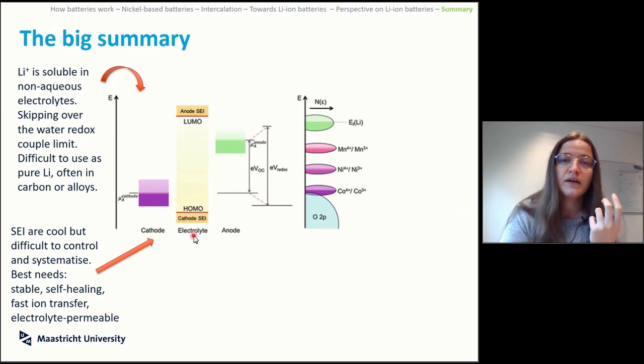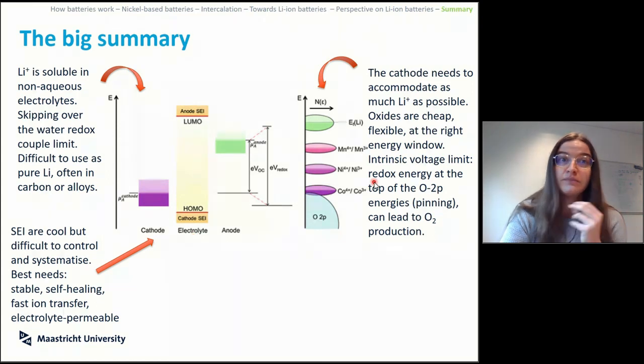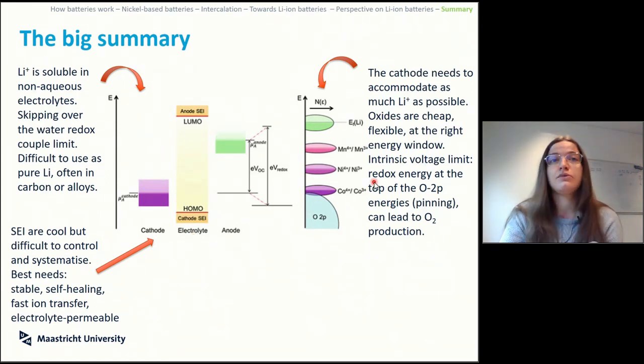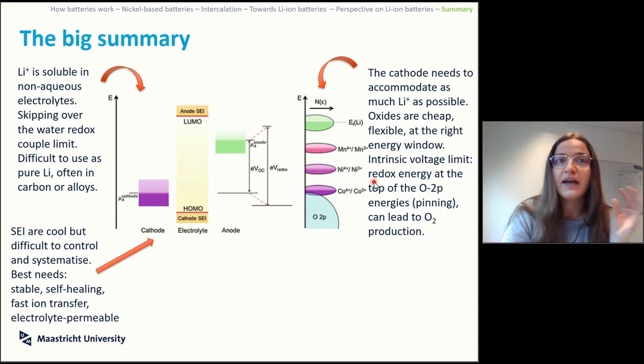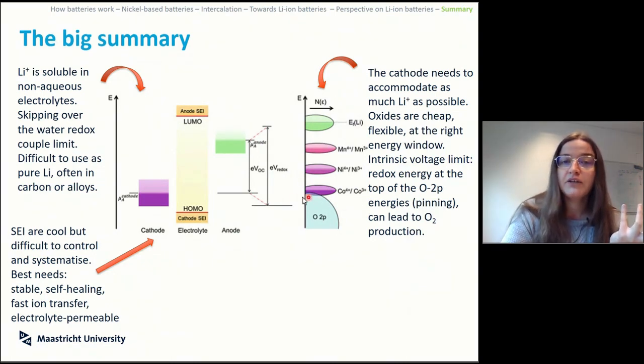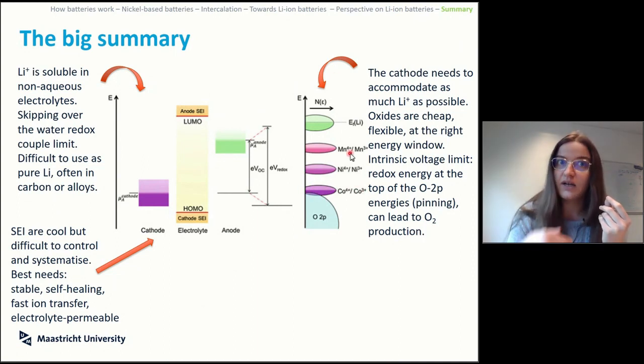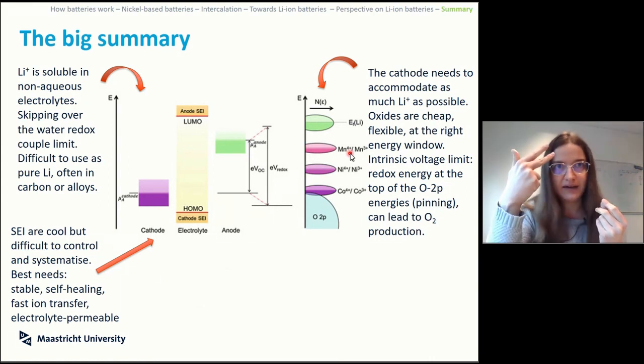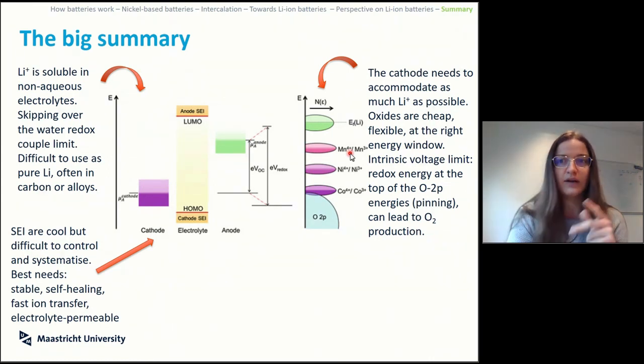The cathode needs to accommodate as much lithium as humanly possible, because you want this to be rechargeable, and the insertion and extraction needs to be within the solid, as your redox couple does the reaction. But you need to remember that the limit, if you're using oxides, is the 2p energy band. You don't want to do electrochemistry on oxygen, and then all the redox couples need to be higher than the 2p band and go like that.